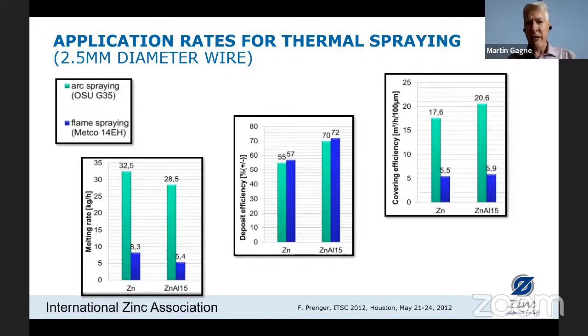And now we finish on the right-hand side graph. Now we're looking at covering efficiency. How many square meters per hour can we cover with a coating that's 100 microns thick? And again, because of the deposition efficiency and the spray technology, arc spraying generally provides much faster coverage rates than flame spraying. And so I compare this to flame spraying is like painting with a brush, and arc spraying is like painting with a roller. There are times where you actually need the detail of flame spraying as you would with a paintbrush, and other times you want to cover large surfaces and the arc spray would be more efficient.